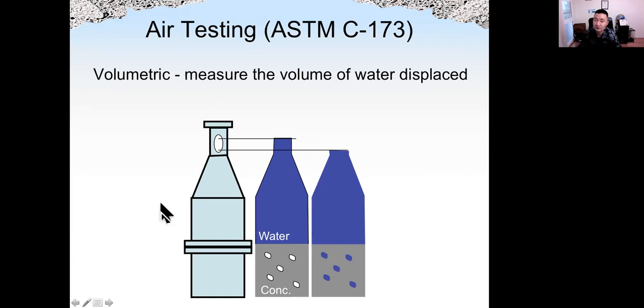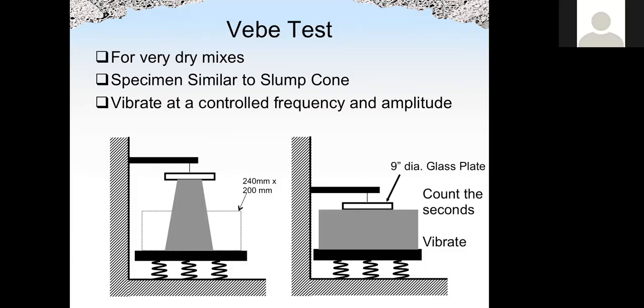Why would you use that really stiff concrete? What applications? Sometimes we want really stiff concrete. For example, when the water cement ratio is very low, the mix will be very stiff, when we want very high strength, or when the concrete has steel fiber in it. When you put fibers in the concrete, the mechanical properties will be very high, the toughness and strength will be high, but the concrete will be very hard to mix, very stiff. I have seen self-consolidating concrete, which is for hard to reach spaces, but I have never seen this one.